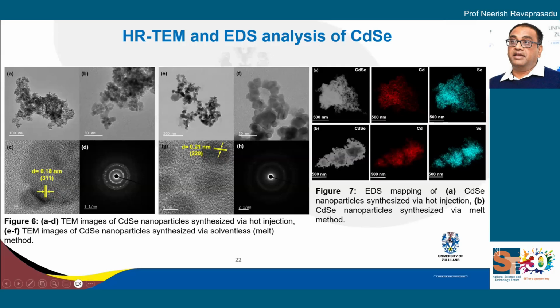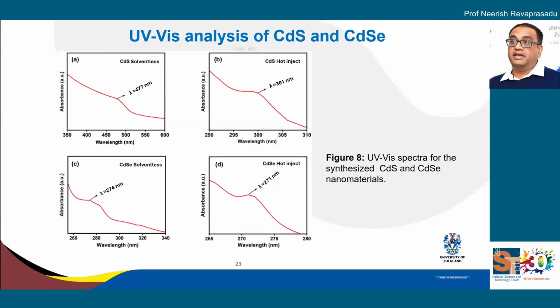So this is the cadmium selenide, similar to the cadmium sulfide. You see very small particles giving you good resolution in terms of lattice fringes, and then the EDS mapping. Those are recently made quantum dots, and the first thing we do is study the optical properties. This is cadmium sulfide, giving you a band edge, and this is the solventless route, and then the hot injection giving you much lower.